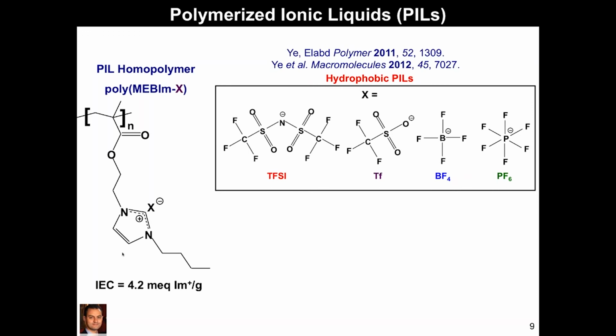And what's interesting is you produce very hydrophobic polymerized ionic liquids, just like PMMA is very hydrophobic. But by changing the anion, you could drastically change the glass transition temperature. And probably what's interesting compared to other ion-containing polymers that you're used to is typically, let's say if you take a typical plastic and you sulfonate it with a strong acid like sulfonic acid to make it an ion-containing polymer, that typically increases the glass transition temperature. In ionic liquids, it's a little different. Typically, when you functionalize typical plastics like styrene or PMMA, it will actually sometimes do the opposite because of the very bulky counterions and their weak electrostatic interactions will actually, instead of acting like an ionic crosslinker, almost act like a plasticizer and actually reduce your glass transition temperature.